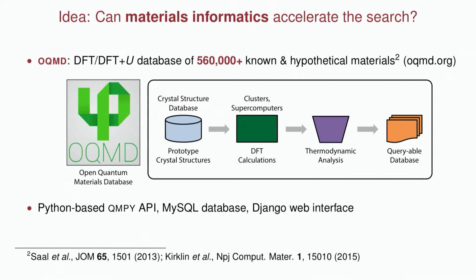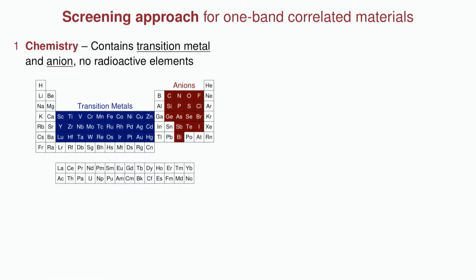So the idea here is we take experimental crystal structures as well as crystallographic prototypes. On our local clusters, as well as supercomputers, we run many, many electronic structure calculations at a consistent parameter set such that we can do interesting thermodynamic analyses and generate this nice kind of queryable database. And we use this to try to answer different questions in material science. So we devised a kind of screening strategy to look for this special electronic property of this single band correlated material based on a few factors.